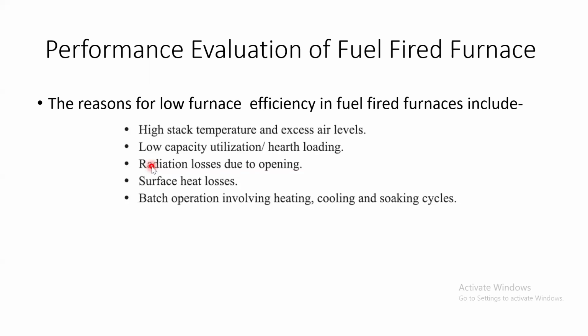Okay. Now, performance evaluation of fuel fired furnaces. Why is the efficiency lower in fuel fired furnaces like FO, and why is the efficiency of electrical furnaces in the range of 70%, but for FO, LDO, the efficiency is around 50% or even less? What are those reasons? The stack temperature is quite high, up to 700 or 800 degrees centigrade, and air levels are excess. That is, we all know that excess O2 is used for combustion, which we have learned in boiler also. Then capacity utilization is low. Suppose the furnace is capable of melting 1000 kg, but because of many restrictions from customers or clients, you could put only 700 kg or 500 kg.